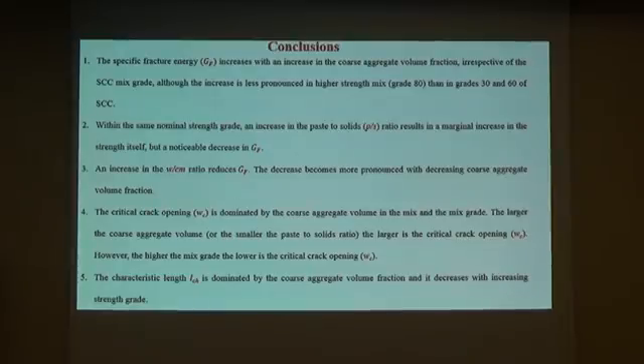Okay. Specific fracture energy increases with the coarse aggregate volume fraction, and this GF decreases with the increase of water to cementitious material, and also with an increased paste to solid ratio, the GF decreases. Critical crack opening is also dominated by the coarse aggregate volume fraction, and the same thing with the characteristic length.